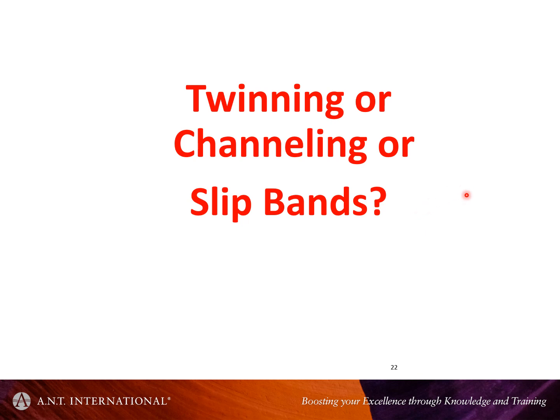I mentioned the ambiguity when you see these bands. Are they twins? Are they channels? Are they slip bands? Channels are also a kind of bulk shear like a twin, but not as regular. But if they're slip bands, so if the slip is localized so it stays on one plane, that's potentially when you could get more intensification, more amplification of stress and failure by that means.